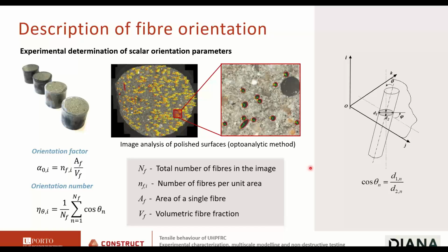So can we get this experimentally? Yes, we can. We can cut samples from our UHPFRC elements, polish the surfaces, and do some image analysis that allows us to have algorithms that count the fibers, and they can even tell us the orientation of each fiber. Okay, so the fibers have a circular cross section. If they are inclined with respect to the polished plane, they will appear as ellipses, and the cosine of the angle of fiber orientation can be obtained from the largest and smallest diameters of these ellipses.